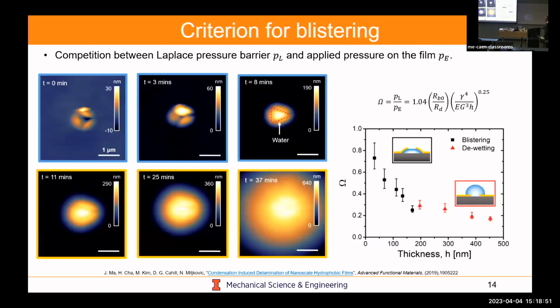So it turns out by using that plate and membrane theory formulation that I showed before, you could actually develop this omega parameter, which is a non-dimensionalized pressure. Think of this as the Laplace pressure, which is being formed inside the blister, normalized by the elastic pressure of that membrane, which wants to stay on the surface. So you need some force to actually delaminate the coating. And so you could think of this omega as essentially, if this Laplace pressure is greater than the elastic pressure, then what will happen is blister formation will happen. So if you actually have this greater than 1, you'll end up seeing blistering form. If it's less than 1, you won't see. And that actually agrees well with our previous results because the Laplace pressure is proportional to 1 over the radius of the defect itself.